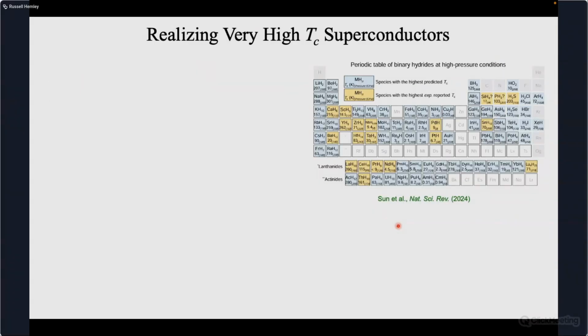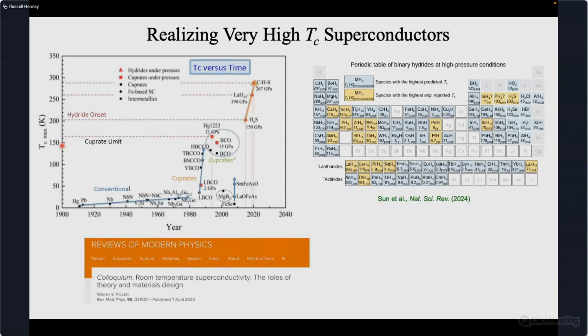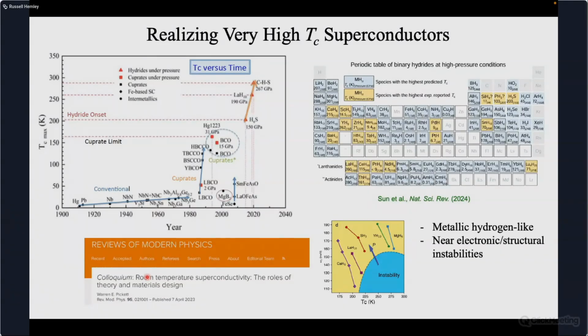So now a wide range of binary hydrides have been studied, and basically the entire periodic table of binary hydrides and their TCs have been established theoretically, and for the most part, where experiments have been done, confirmed. So now we have a binary hydride superconducting periodic table here. And we have this plot showing the maximum TC versus year, starting with mercury, going up through the cuprates that I mentioned, the iron-based unconventional superconductors, and now in this regime at very high temperatures, approaching room temperature, the hydride field. This is from a beautiful paper written by Warren Pickett, who laid out some of the ideas that really confirmed some of the early conjectures by Neil Ashcroft, that these are metallic hydrogen-like structures, and also that the highest TCs occur near electronic and structural instabilities.